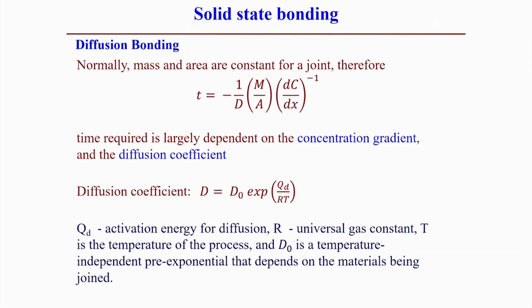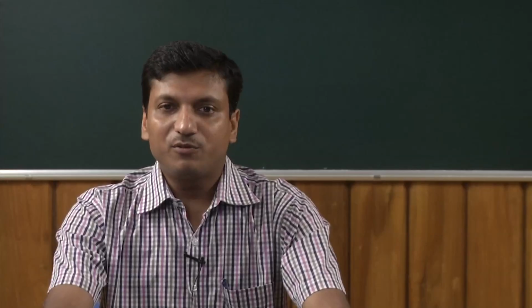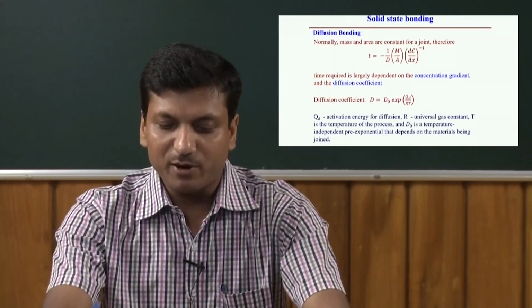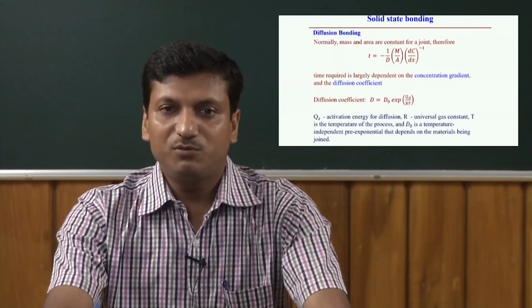So the time requirement depends on these two parameters, but actually the diffusion coefficient may not be constant; it also depends on the temperature, or it is a function of the temperature. So D can be expressed like that, D0 into e to the power minus Qd by RT. Qd is the activation energy for diffusion, R is the universal gas constant, T is the temperature of the process, and D0 is a constant that is independent of the temperature, but of course it depends on the material being joined. So from this expression we can estimate the diffusion coefficient if the other parameters are known to us, or maybe the time requirement for the diffusion bonding.